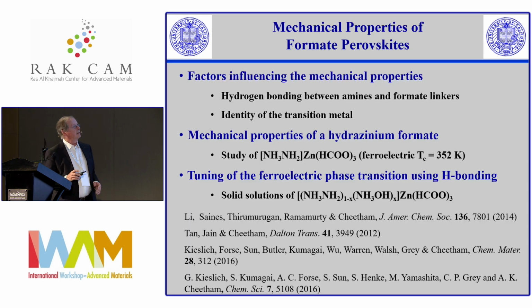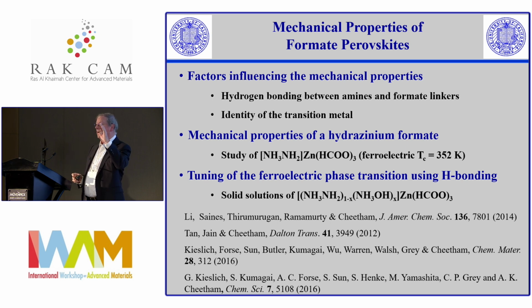Well, we did a lot of work on the mechanical properties of these formates, which I don't have time to go into, but the mechanical properties are strongly influenced by hydrogen bonding between the amines and the formates, the transition metal itself. And so, for example, we looked at this hydrazinium system, which is a ferroelectric at up to 352 Kelvin.